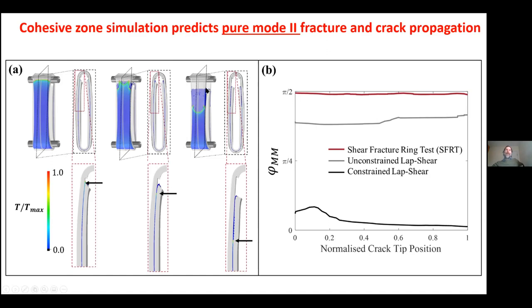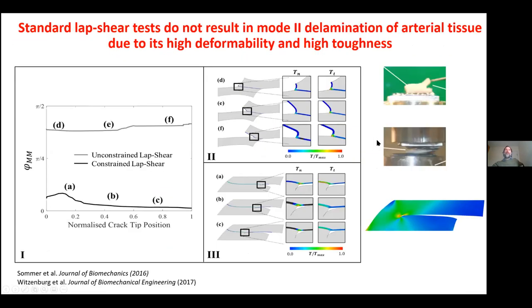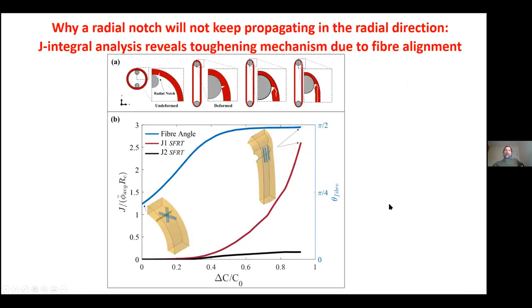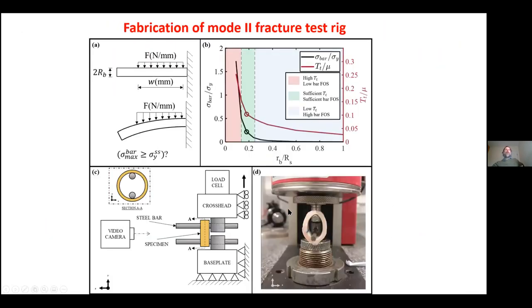If this test works, we believe that we will have developed a fracture test that gives us a pure mode 2 fracture of an artery, which you fail to get from a lap shear test, from this test, or from this test. So we did some design of experiment. We had to make sure the loading bars are strong enough to carry the force required to get up to the critical strength, because these arteries are very tough. It takes a lot of force. You have to deform them a lot before they rip.